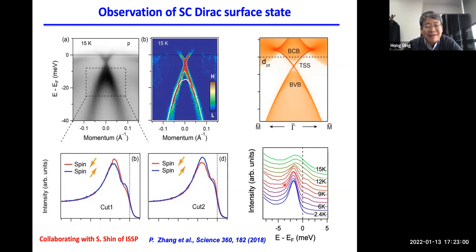And your ARPES data is very lousy. And it took us three more years, when my student Peng Zhang became a postdoc in Shin's group, and we collaborated and used the super high resolution laser ARPES to actually, for the first time, demonstrate that indeed you have a Dirac cone. This Dirac cone is actually spin polarized. By using the spin resolved ARPES, this actually proves what we observed is a surface state, and this surface state opens up a superconducting gap below the bulk Tc, 15 kelvin. So that satisfies all the criteria of Fu-Kane's model.